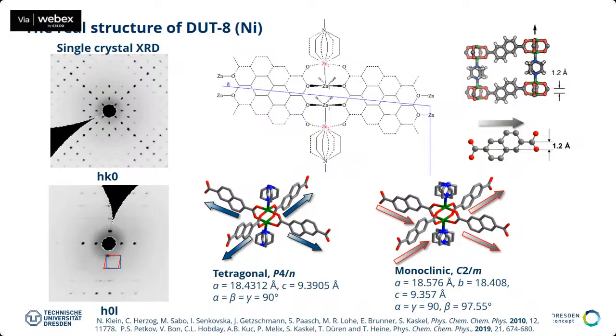But this bothered us very much for a long time, and we were very suspicious about what is going on there. And for this, a cooperation with Andrew Goodwin in Oxford was very important for us. And we realized more in detail that the problem here is that the naphthalene dicarboxylate linker is not a linear linker. It has a very small but distinct step function, 1.2 angstrom basically. It's like a stair if you're going up. And if you have stairs that go up, then there are also stairs that go down. And this creates a lot of chaos or disorder in this kind of structure.